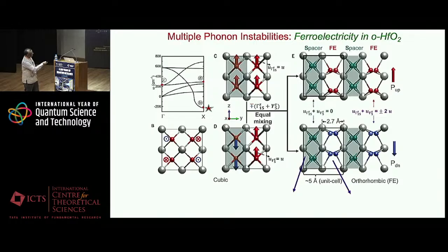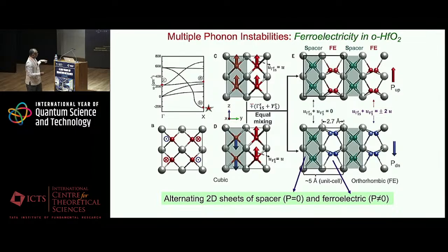And you will see they condense in the low temperature phase with equal amplitude. If you add up these two phonons, you will get zero dipole moment in one spacer layer and a large dipole moment in another layer. So this is basically a sheet of oxygen atoms which get dipolarly polarized. This is remarkable. You have alternating two-dimensional spacer and ferrodipolar sheets in this hafnium oxide.